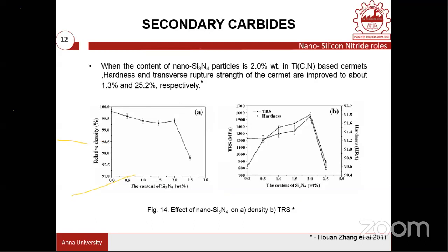But what is the effect of adding a nano kind of material over there? Supposing you have a rim structure formation, you assume TiCN and you have an inner rim formation. If you add a nano-sized material, this nano-sized material will be dispersed uniformly in the inner rim as well as in the outer rim. The outer rim is a metallic phase. So fine distribution of these nano precipitates or nanoparticles in the inner rim as well as in the outer rim will prevent the crack propagation, and also delay the crack propagation, and also deflect the crack propagation. As a result, the toughness value would be increased. So here the silicon nitride is not only going to improve the hardness value, but it is also going to improve the toughness value by uniformly distributing itself in the inner rim as well as the outer rim.